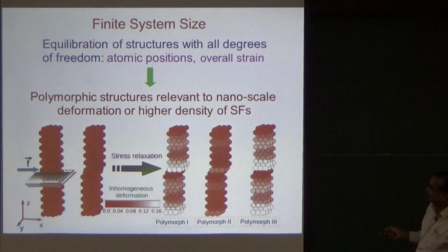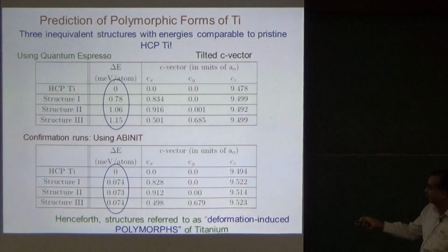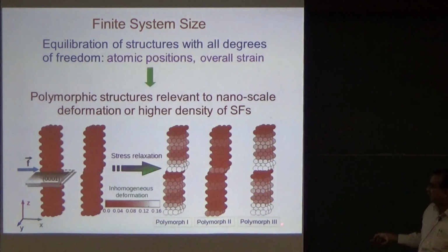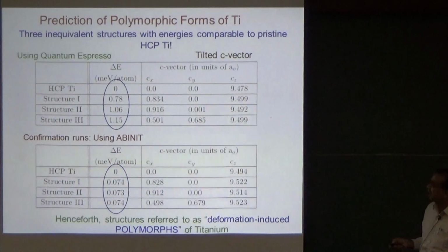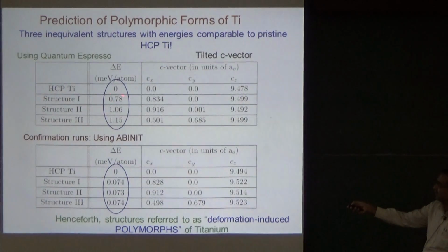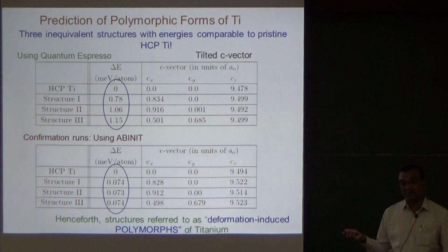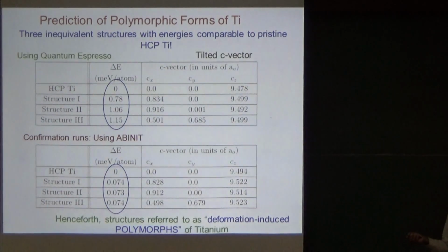So basically what we find is instead of nucleating dislocations, you can have inhomogeneous strain here and new polymorphic structures which can accommodate fairly large shear strains in these metals. And the energies of those polymorphic forms are fairly low. It's less than a milli eV per atom, and we reproduce it with different methods that are available, and it's quite a robust result. And it applies to all the HCP metals except for zinc. Zinc is a very anomalous HCP metal in the sense its C by A ratio is totally different from the ideal C by A ratio of HCP structure.